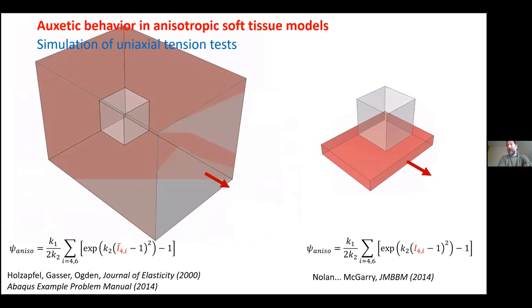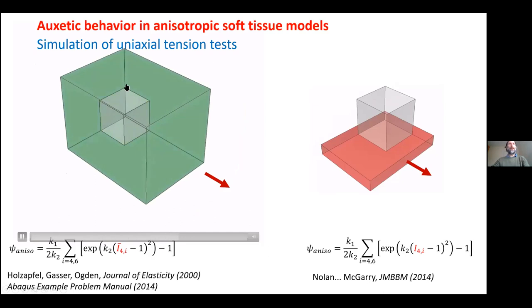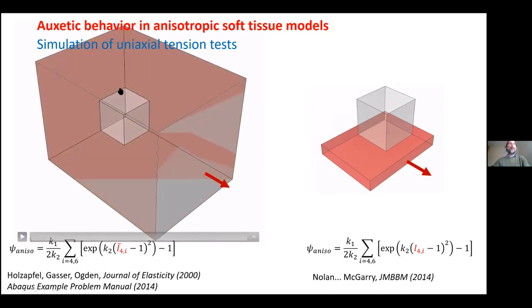If you go into Abaqus, for example, and you try and use an anisotropic hyperelastic model, which basically says we have fibers in a matrix, and you do a uniaxial test, so I'm going to play this again. What you find is when you stretch the material in this X direction, it expands outwards in the Y and the Z direction, which is completely unphysical.